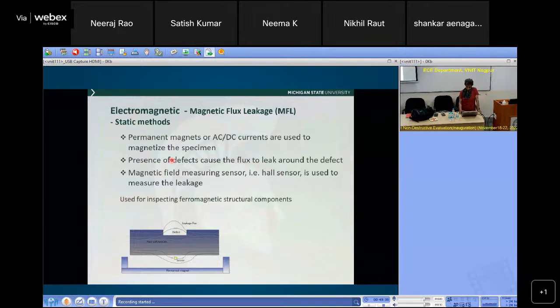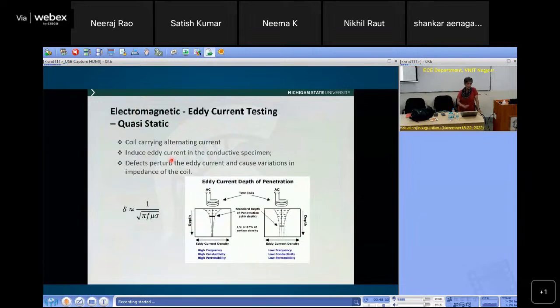Okay, so what do we do for aluminum? We use the eddy current sensor. Again, it's such a simple method. The underlying physics is very, very simple. The sensor is simply a coil. You excite it with an alternating field. Current sets up an alternating field. That field will then, you have to have a conducting sample, set up an eddy current inside the sample. Eddy current is always in the opposite direction. If the exciting current is like this, the induced current is in the opposite direction. And so the net flux linkage, there's a flux associated with eddy current. Again, I'll talk more about it, doing it very, very quickly here.